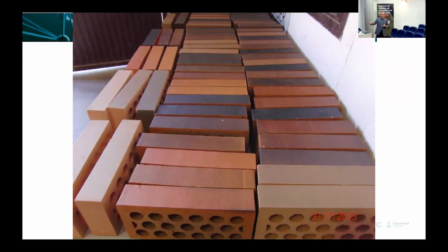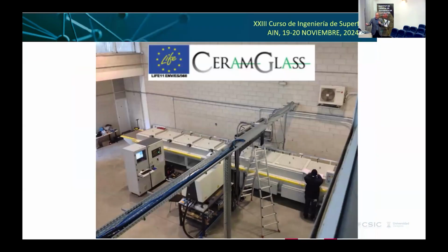And so you can see this with the same composition, depending on how much intensity of the laser and how fast or slow you go, you can get all these different colors and seal them. And then we built a different furnace for another project just to save energy. So this was an electrical furnace, and it was specifically built to treat flat samples.